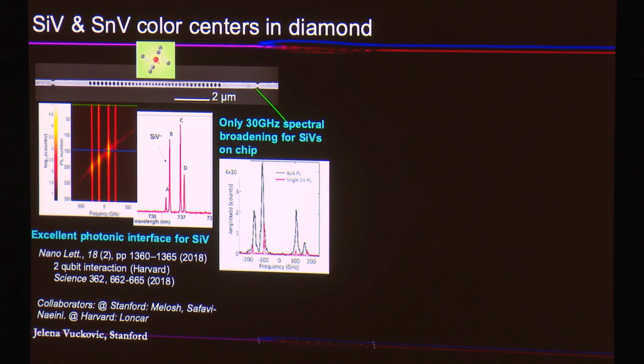Then we've also shown that we can grow these color centers on a diamond chip in such a way that we have only 30 gigahertz inhomogeneous broadening. And this can be seen in this spectrum. For those of you who are experts, the spectrum of a single silicon vacancy color center is in red, and the spectrum of the ensemble is in black. And there is only a 30 gigahertz distribution. And 30 gigahertz is much, much smaller than what we previously had for quantum dots. And as you'll see in a moment, it is something that we can control and overcome with a variety of methods.